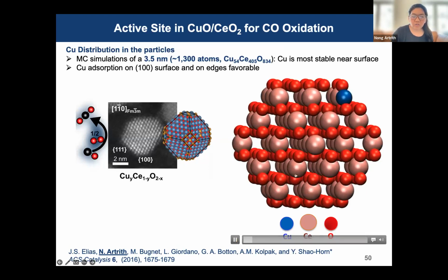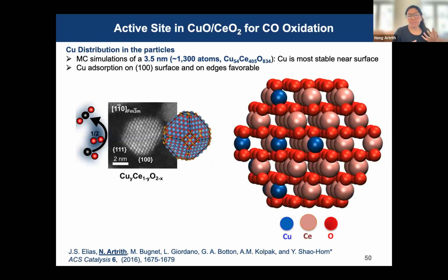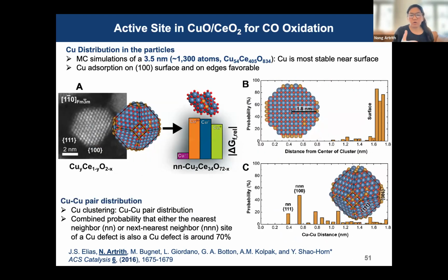In this Monte Carlo simulation, the copper is in blue, the cerium is in pink, and oxygen is in red. You can see that we ran long Monte Carlo simulations to find where copper really sits in the structures. At the end, after many different simulations, like a million steps of Monte Carlo, we take only the equilibrated structures, and then we find where copper sits in the structures. Most of the time, we see that the copper likes to stay near the surface, like the 100 surface or 111 surface, as you can see here after we collect the final structure from Monte Carlo simulations.